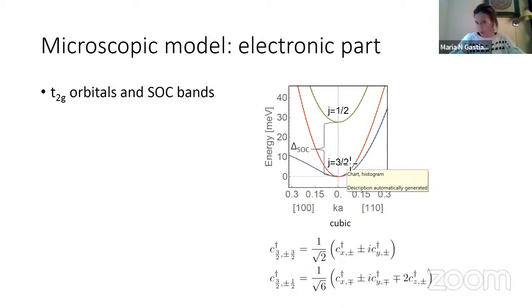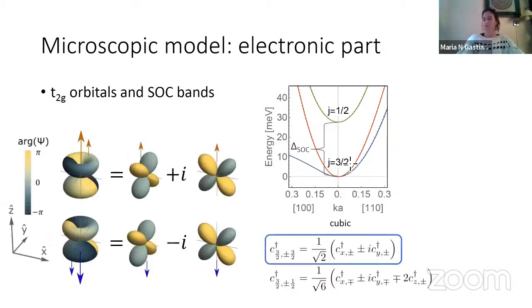Because I'm going to be using these bands to show how the coupling to the transverse optical phonon mode works, I'll be using this kind of picture. With spin orbit coupling, you are adding an effective L equals 1 orbital degree of freedom from the t2g orbitals, with spin 1/2. For example, this one here, the 3/2 plus minus 3/2, is mixing just two of the orbitals. I'll focus on those particular states, because instead of three orbitals you're only mixing two, and it's a little bit simpler to show.